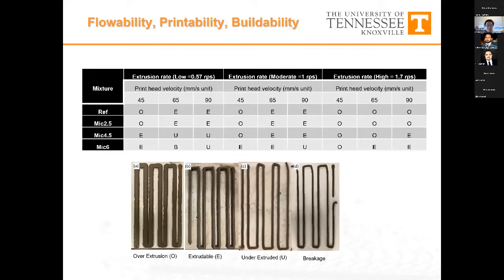So this is the printability test that we ran on those mixtures. And methodology-wise, we have seen a lot from the previous two talks, and I'm not going to repeat it. I'm just going to talk about the conclusion here: if we look at different volume dosages of the micro-sized PCM versus the extrusion rate and print speed that we tested, all the E's right here are the acceptable printing parameters that we found from our testing.